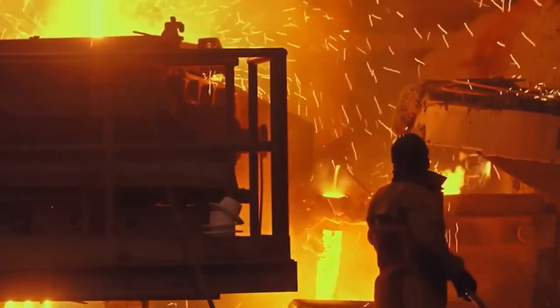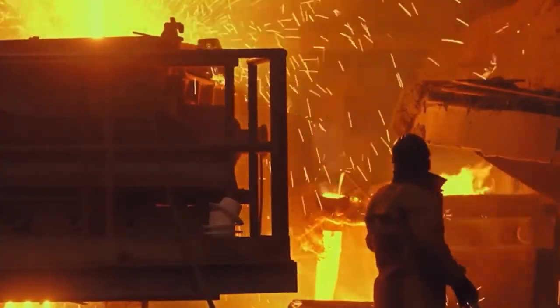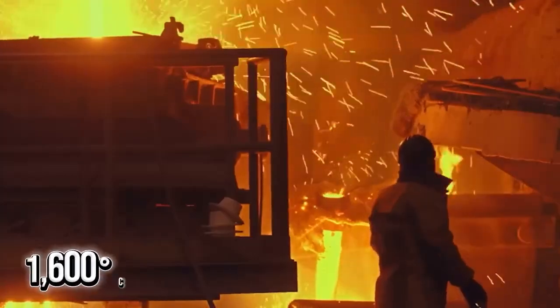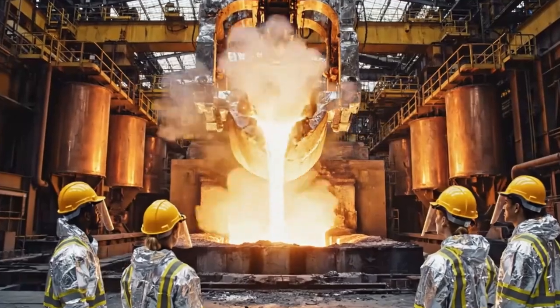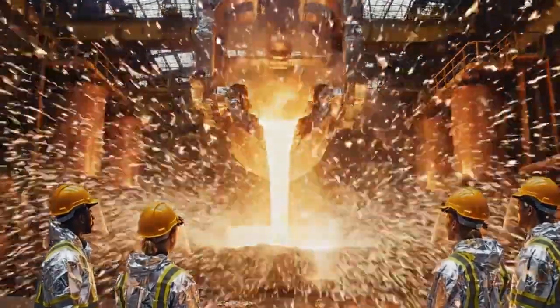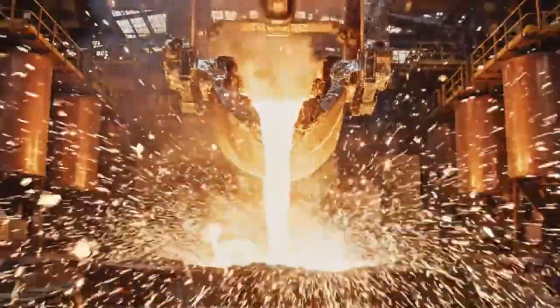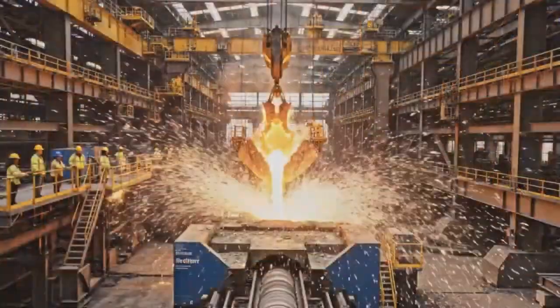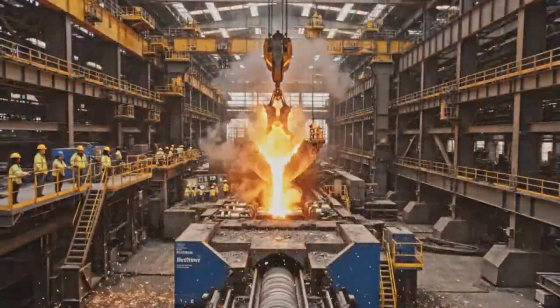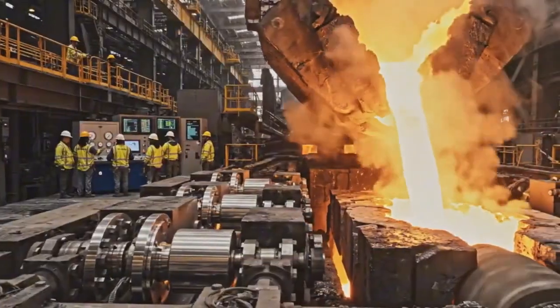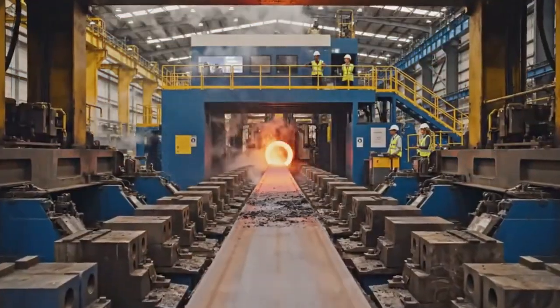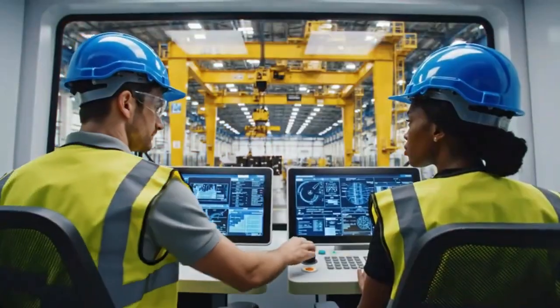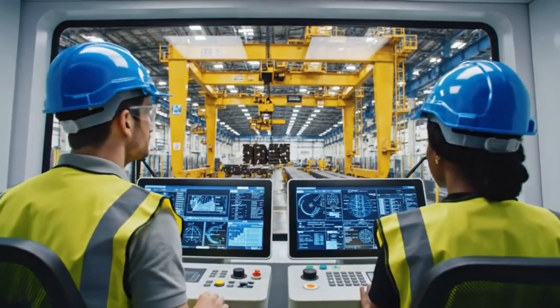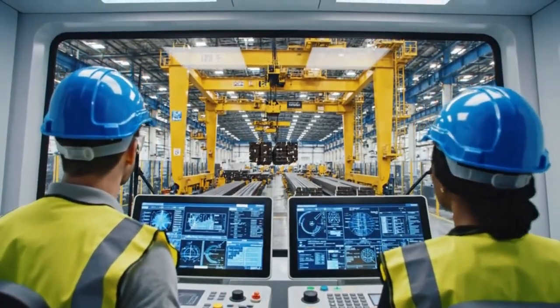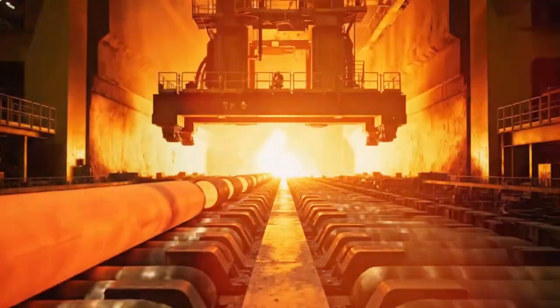The first stage is the melt. Furnaces hold hundreds of tons of raw scrap steel and iron ore, heated to nearly 1,600 degrees Celsius. The molten steel spins and glows white-orange, bubbling under oxygen lances that remove impurities like sulfur and phosphorus. This isn't just melting metal, it's creating molecular order. The furnace crew measures composition constantly with automated spectrometers. Each batch must hit exact targets or it is rejected before pouring.